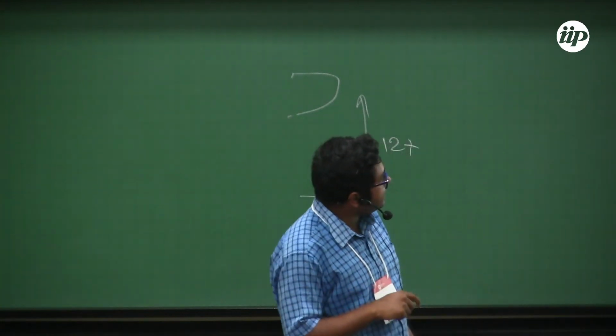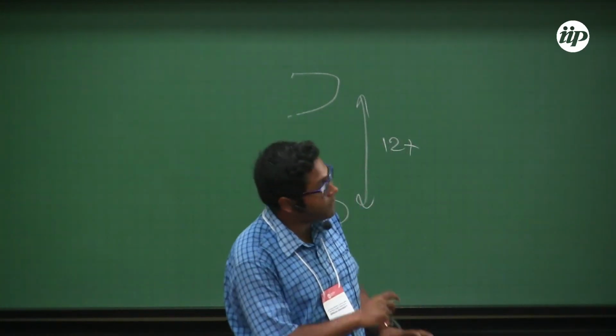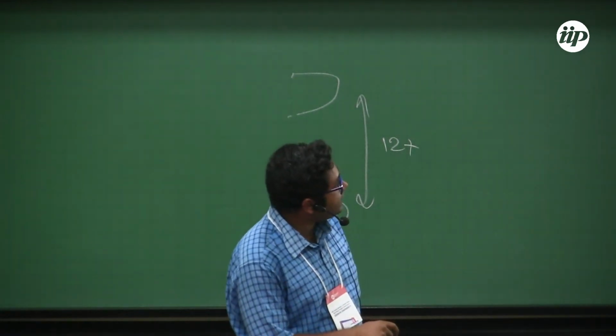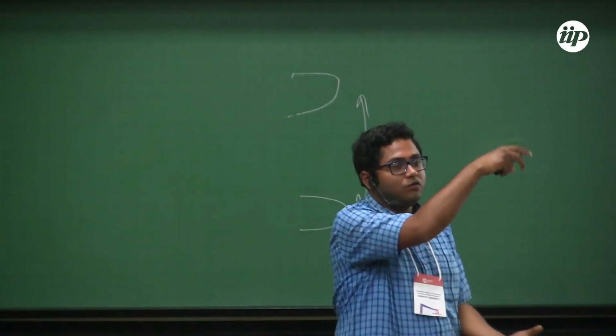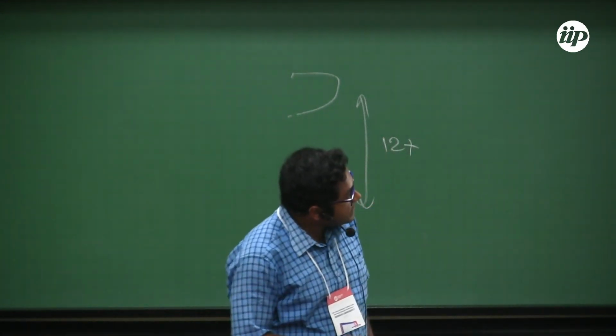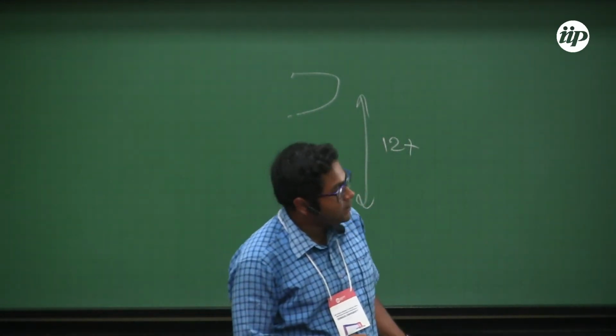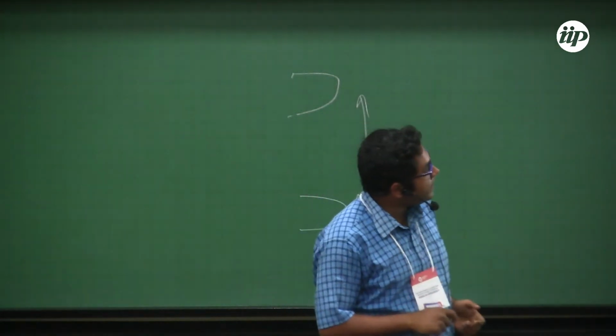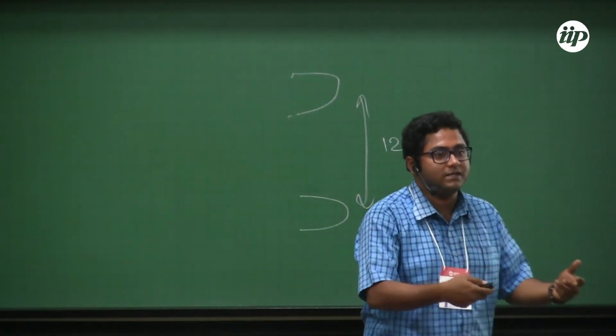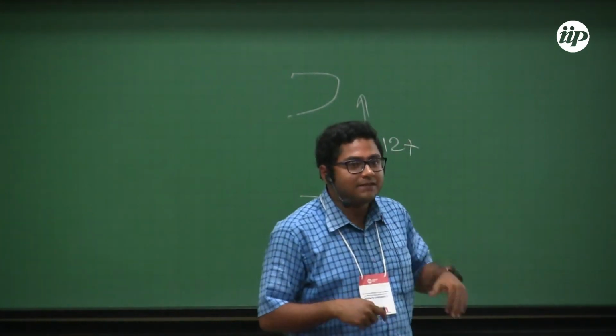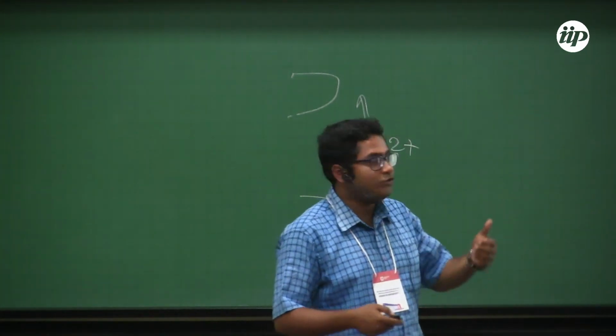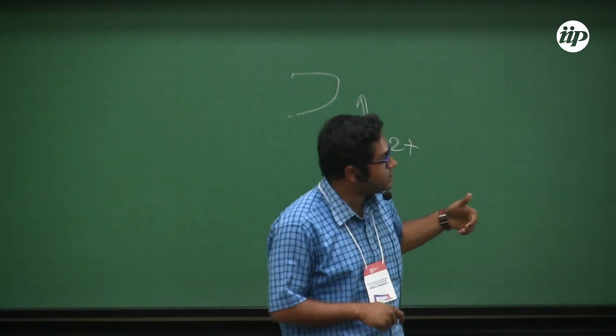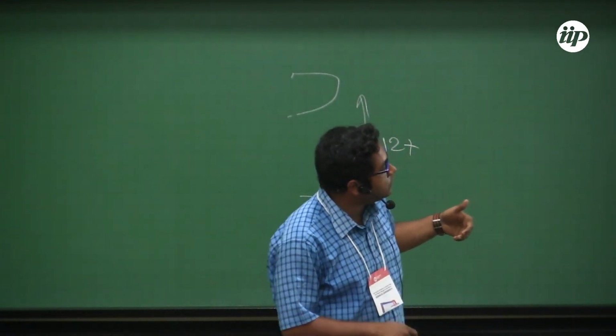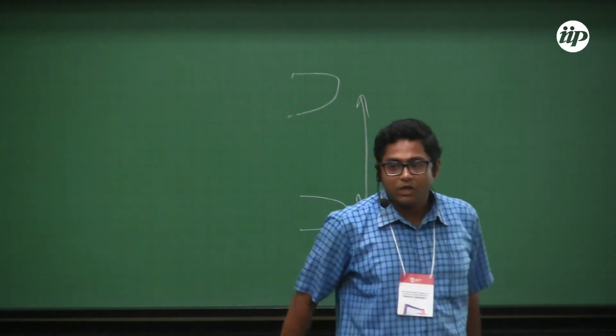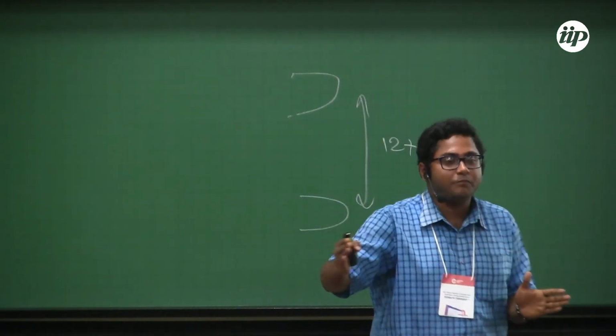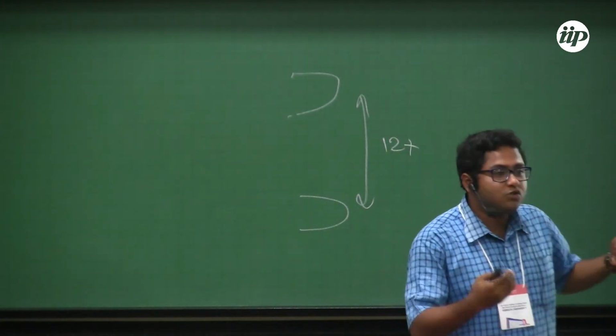So what is happening is that if you have a very high disorder potential, bare disorder, to be very high at i, the density would be very low because electrons don't want to sit on a high hill. Since the density is low, this Gutzwiller factor will then increase. As a result, the effective hopping into that site will increase. And the density would no longer be as low as it was in the bare potential. And if you think in terms of a renormalized effective potential, this renormalized potential will not be as high as it was given.